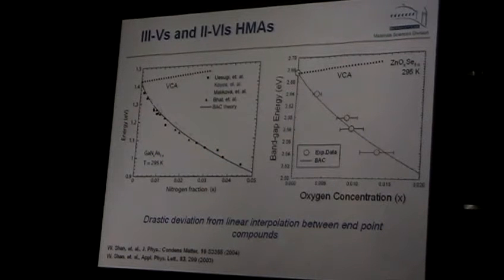And this in fact led people to use it for so-called vertical cavity surface emitting lasers, and this is a successful business right now, making this laser, because you can move it to frequencies of 1.3 and 1.55 micron. So it was a success. Despite the fact that the material was already so successful, people didn't really understand what was going on, why there was such a big change in the band gap, in the wrong direction.